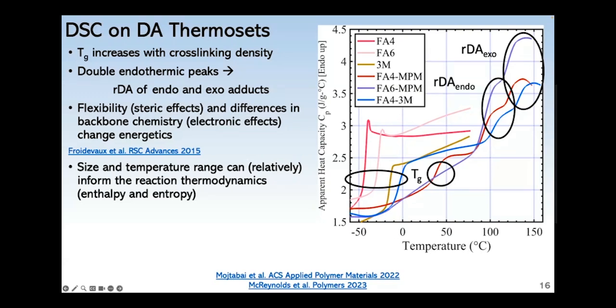And if you examine the peak size and the temperature range, you can get an idea about the concentration differences or the reaction thermodynamics among the different Diels-Alder thermosets. For example, if you look at Fa4 MPM and Fa6 MPM, they occur in the same temperature window, which was unsurprising because they have the same or identical chemistry, they just have a difference in structure. But the retro Diels-Alder peaks for the Fa4 tris-maleimide compound are shifted or occur at later temperatures, which you could say is because they're more stable. You could argue that from either an entropic or enthalpic argument.